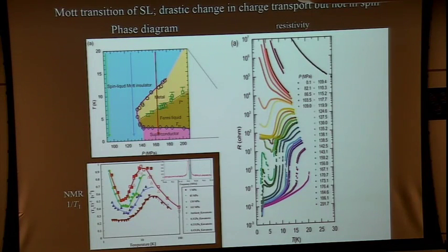Okay, more interesting data is the evolution of the behavior of the charge degrees of freedom and the spin degrees of freedom. The right-hand side figure shows the evolution and the change of the temperature dependence of resistivity. This is the ambient pressure data, insulating over many decades. Okay, for example, 85 megapascal here, the spin liquid insulator. And along these lines, the resistivity behaves like this. Very good insulator.